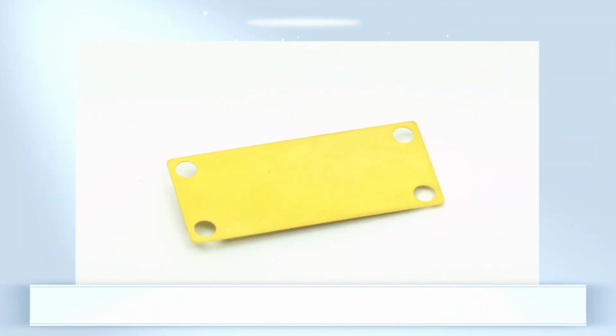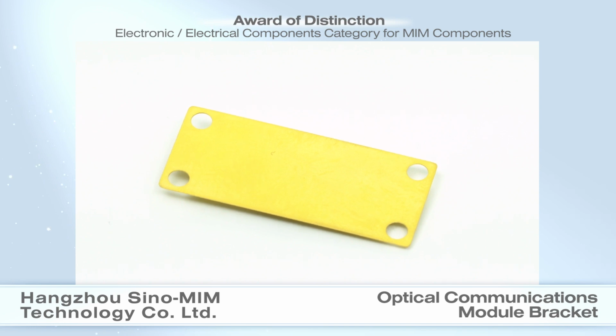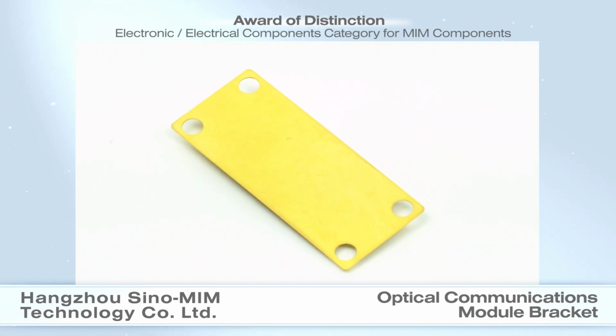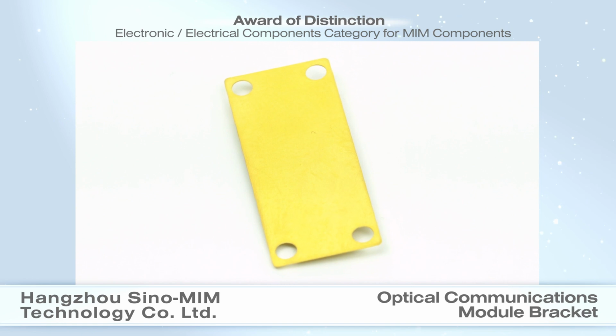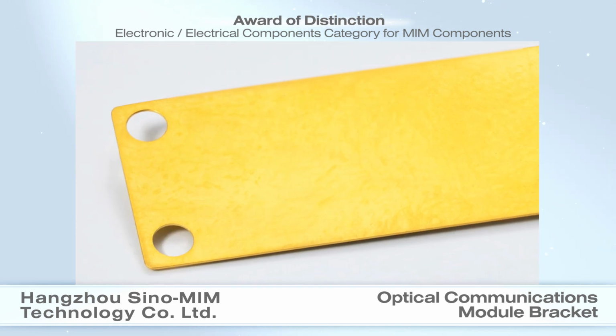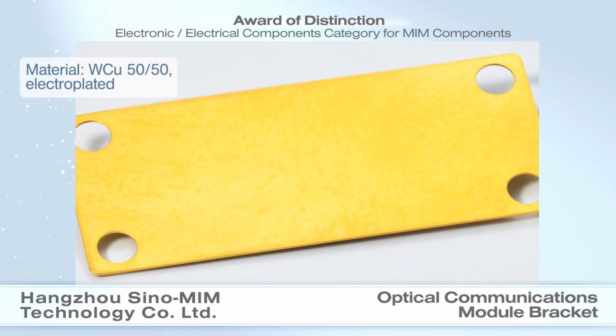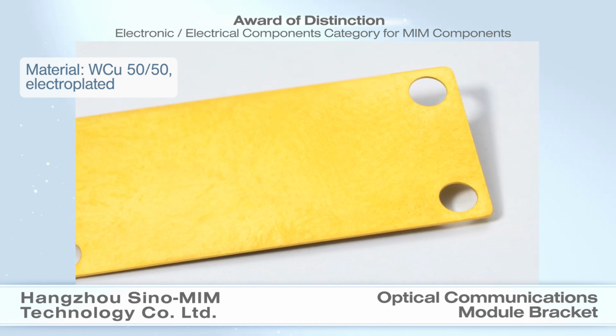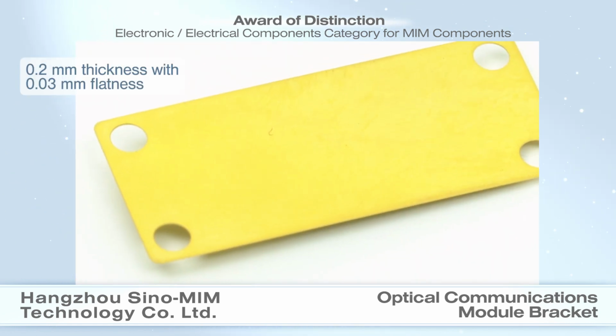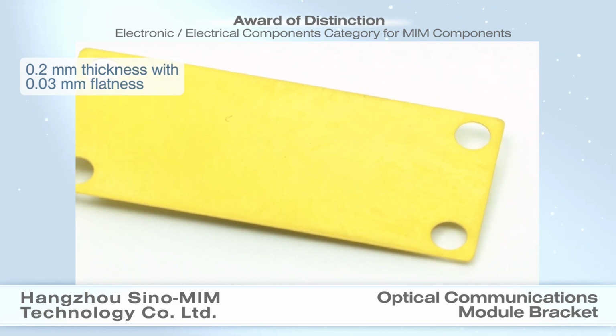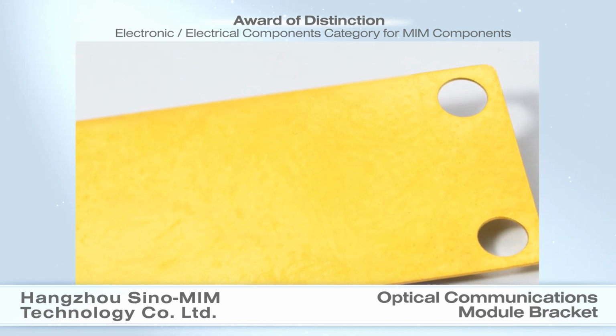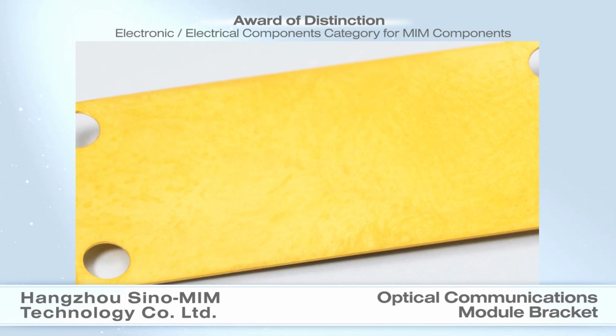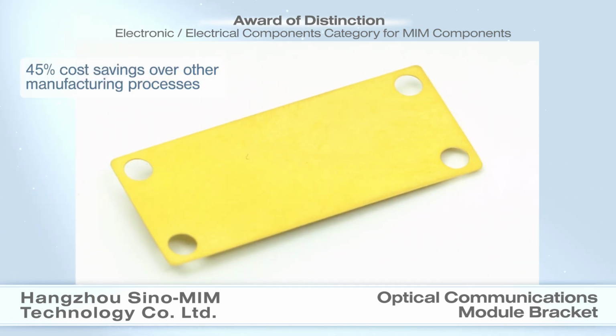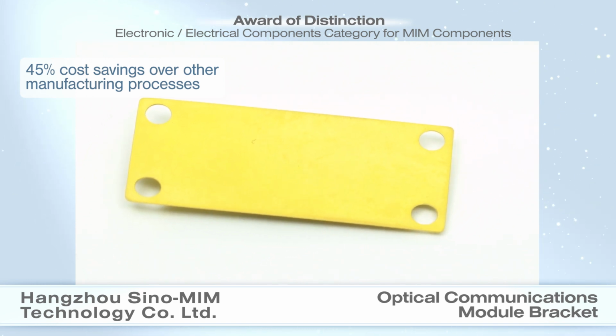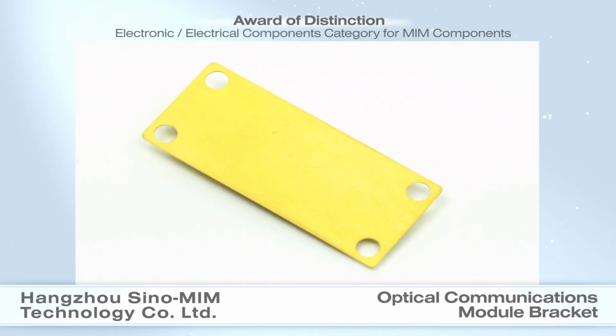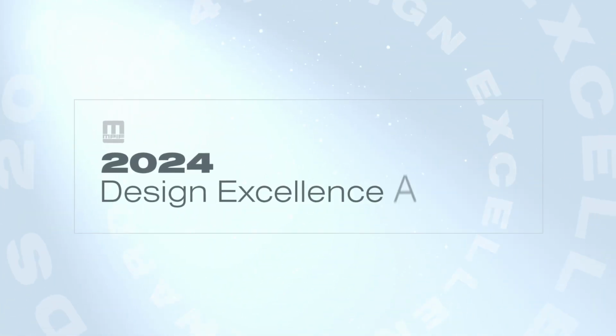Hangzhou Sino-Mim Technology Company Limited received an award of distinction in the electrical components category for MIM components for an optical communications module bracket. Used as a heat dissipation module in an optical communication 5G base station, numerous heating components are mounted on the bracket surface, which serves not only as the mounting base, but also conducts and dissipates heat. This ultra-thin base plate has a flatness requirement of less than 0.03 millimeters. MIM processing cut the product cycle time for this electroplated 50-50 copper tungsten bracket while reducing the cost by 45%.